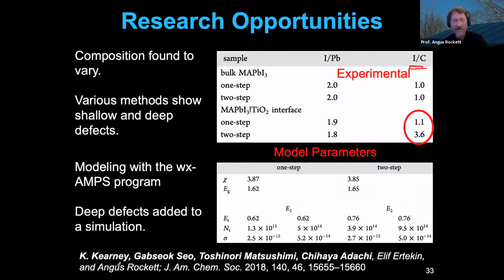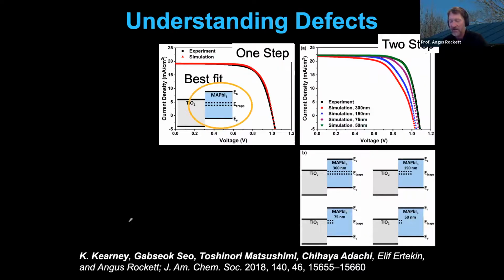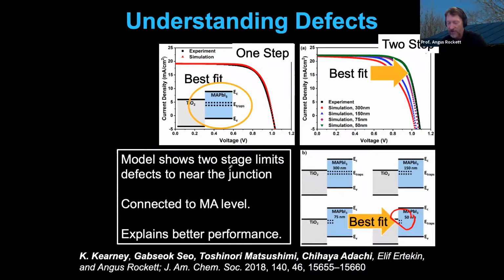My student, Kara Kearney, did this in collaboration with you all, and she used a so-called WX-AMPS computer program, added deep defects to the simulation, and for the one-step material, she showed a best fit where she had those deep defects, those problem defects, all the way through the MAPI material. Whereas with the two-step process, she found that the best fit was with those defects restricted to near the junction. So her model showed that the two-stage limits defects to near the junction where they're less harmful. She connected that to the methylammonium level in the material and explained the better performance of the device.